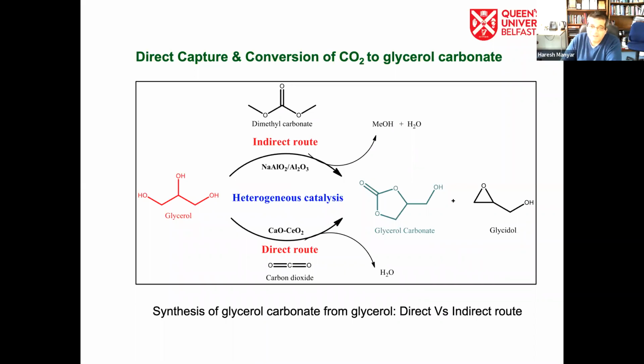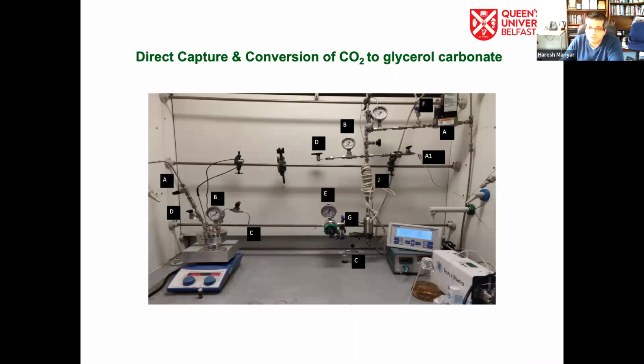In terms of the direct route, we can directly capture CO2 from the air or from the pressurized gas phase, and then convert it into glycerol carbonate. In this case, we are using dual function materials, like calcium oxide and cerium oxide. The function of the metal oxide is to capture CO2, and the other part of the material is to react it to glycerol carbonate. This is the reactor setup shown here on screen. We have both kinds of reactors here. On the left-hand side, we have the batch reactor. On the right-hand side, we have the continuous flow reactor.